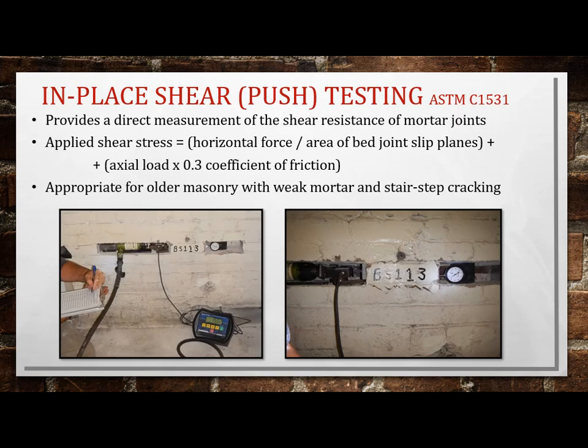So here's a test underway. You push it, and first movement is failure. And so you can determine the shear strength by your horizontal force divided by your bed joint slip planes, which like on a brick, it's about 30 inches square top and bottom.